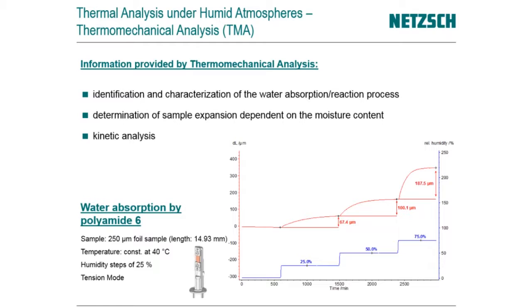You see also that we can use it for kinetic analysis, as we have again the same kinetic procedure. Of course, it's the same process here. And you see that you have again a quantitative analysis of each step independent of the amount of humidity of the surrounding atmosphere. So thermomechanical analysis is also able, as a standalone method, to identify and characterize the process.